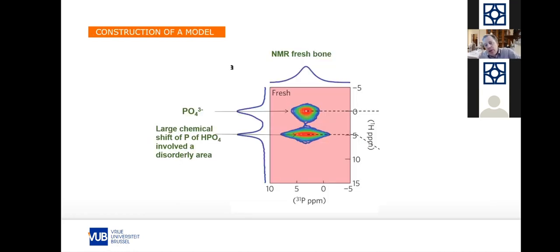What is important here is, if we want to make a model of the bone, for that we are always going back to experiments. And we see that, for example, if we do a 2D NMR diagram, we have proton and phosphorus, and we see two species of phosphorus. This means that we have a phosphate and a hydrogen phosphate group. So in our hydroxyapatite or our calcium phosphate system, we should have both types of phosphates.